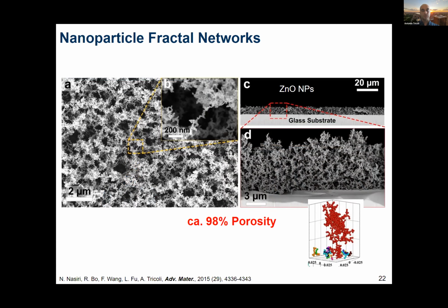And this is with no sintering, like in this case. If we let the particles coalesce and sinter during deposition, then we can control the porosity down. And this is often necessary to obtain a more stable structure for use in liquid solutions, such as electrolysis.